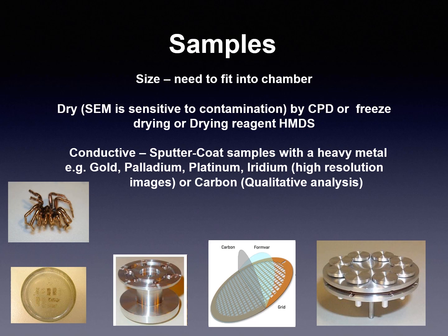Samples must be of a size that can fit into a chamber. The sample must be dry. You can either use a critical point dryer, freeze drying, or a drying reagent like HMDS. It's important that the sample is conductive, so you can use a sputter coater and coat your sample with a heavy metal, for example gold, palladium, platinum, or iridium for high-resolution images, or carbon for qualitative analysis.